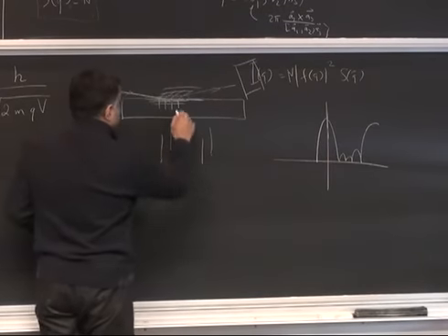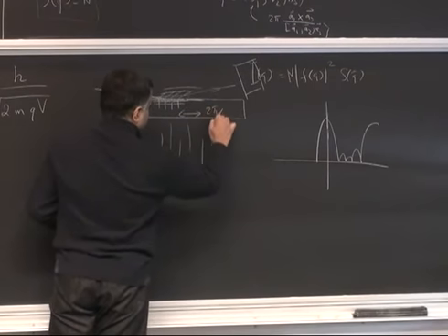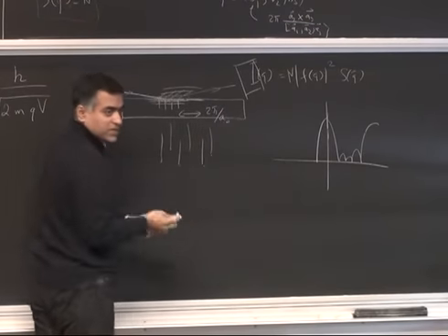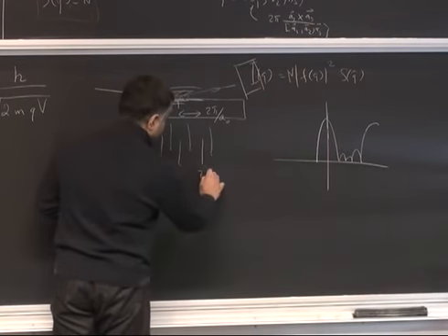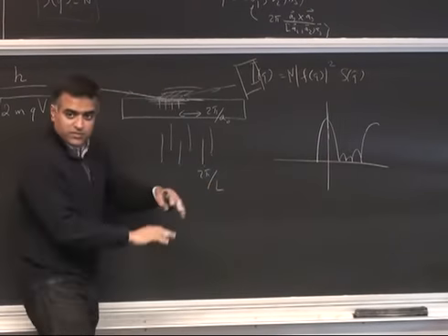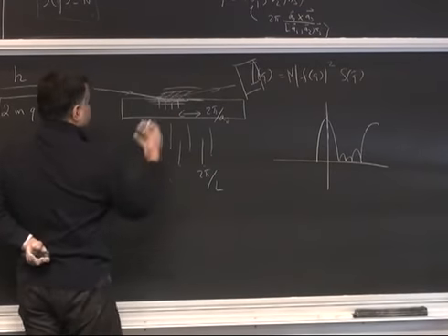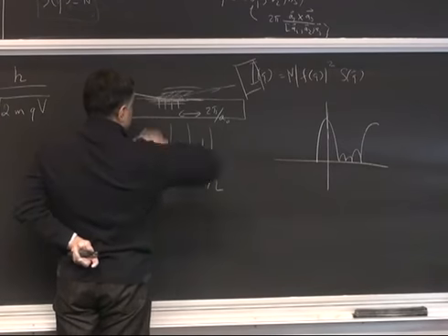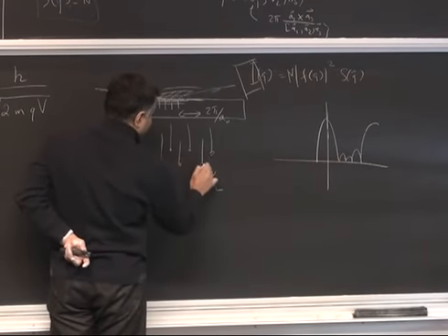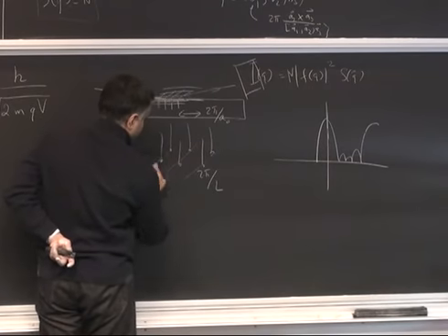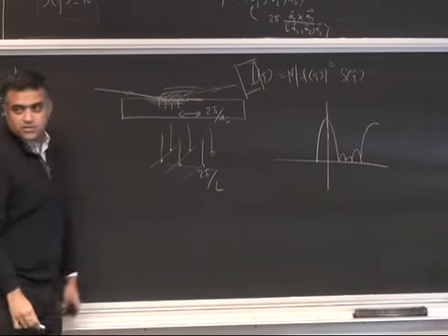Therefore, in the plane of the 2D crystal, the lattice constant is indeed 2 pi by a naught, whatever the distance between the atoms is. But out of plane, it is 2 pi by a very large number, so it's like 0, and all the points join together. So the reciprocal space map of a 2D sheet is the reciprocal lattice point of the 2D crystal in the plane, but outside of it, it's all continuous. You can think of it that way.